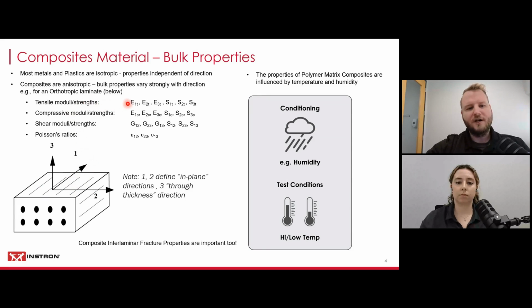still there are all kinds of things that you need to determine to fully know the properties of your material. So for example, you would need to check the tensile strength of your material, as well as the moduli of your material in the tensile direction, in all 3 directions. So in direction number 1, 2, and 3, you need to test that material to fully determine the tensile strength and moduli. The same is true with compression, because composite materials are usually much weaker in compression than they are in tension. So you need to do all those tests also in compression, which usually involves a lot of fixturing. The same is true then with shear. So you need to determine all the different combinations in shear, and then as well for the Poisson's ratio, which we'll touch on a little bit later.